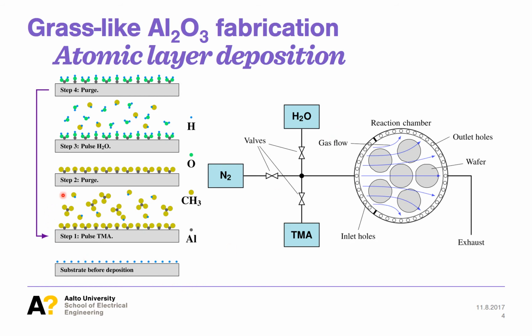First, a pulse of trimethyl aluminum is introduced, which reacts with the surface of the substrate. The reaction has enough time to saturate so that aluminum methyl compounds cover the entire surface. At the same time, methyl groups react with the surface hydrogen, releasing methane. Next, the reactor is purged with nitrogen to remove unreacted precursors and reaction products, thus preventing any gas phase reactions of the precursors. After that comes the water pulse.